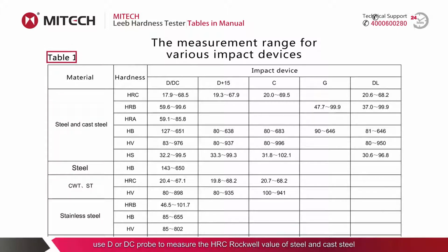As shown in the table, use the D or DC probe to measure the HRC Rockwell value of steel and cast steel. The measuring range of the D or DC probe for steel and cast steel is 17.9 to 68.5 HRC. The measuring range of the C probe for alloy tool steel in HRC scales is 20.7 to 68.2. Please refer to the table for the corresponding hardness units, corresponding materials, and probe range. For example, measuring the HRC value of steel and cast steel with a G-type probe won't work because the table entry is blank. According to relevant international standards, there is not a specific scope.